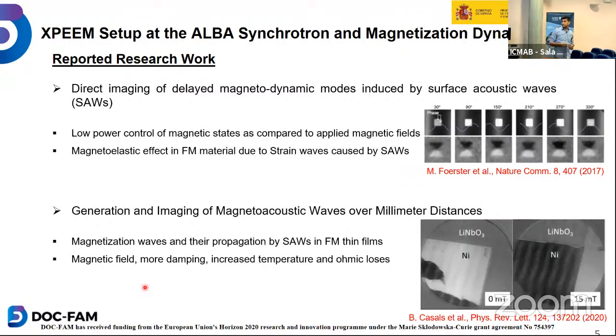Another paper reported nickel with surface acoustic waves on lithium niobate. This is a piezoelectric material, and it generates surface spin waves in the ferromagnetic material and changes the magnetization dynamics. At zero magnetic field, we don't see the rise of spin waves. But at 15 millitesla, when we apply the magnetic field, we see quite strong spin wave motion and propagation. But when we apply the magnetic field, we face more damping, due to which there is a temperature rise and there are losses. That's why we are moving towards surface acoustic waves.